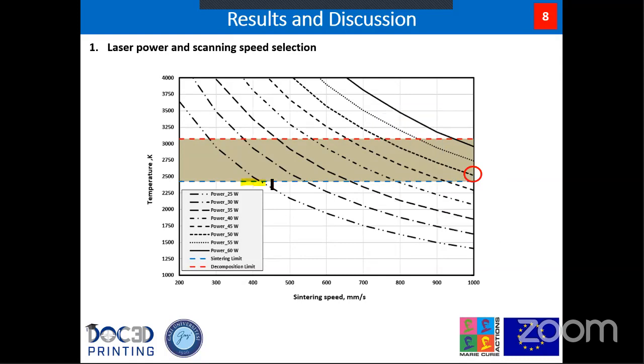You can see here this line is the sintering limit, and the above line, the red dashed line, is the decomposition limit. So all the values that lie between these two limits can be used in SLS of silicon carbide. The values above the decomposition limit cannot be used because decomposition will happen, and the values below the sintering limit cannot be used because sintering will not happen for silicon carbide. So we can only use the values inside this area.